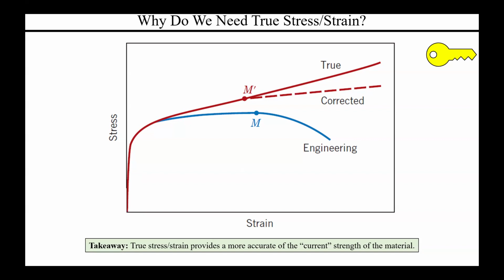So it's what happens if you start off with a square area within your cross section. But by the end, you have some weird jagged topology that is very complex. Area is not necessarily easily quantifiable anymore, but you're still using a simplified metric to gauge the area. What this corrected curve is doing is it's accounting for that, right? It's accounting for the fact that you could potentially have a very complex stress state occurring within that failure region. So it accounts for the overcorrection that the true stress definition is going to have in it.